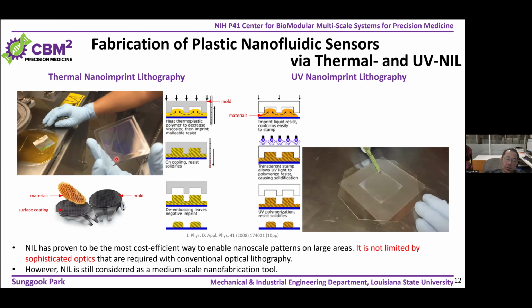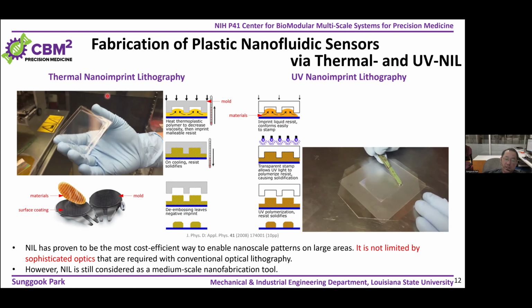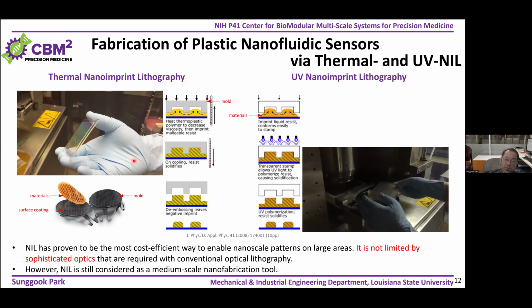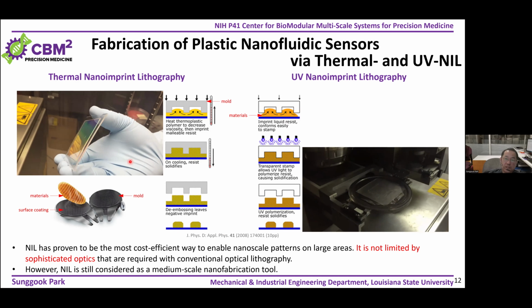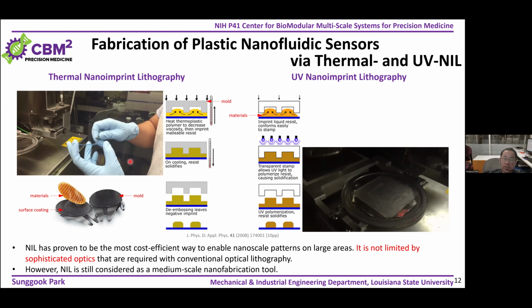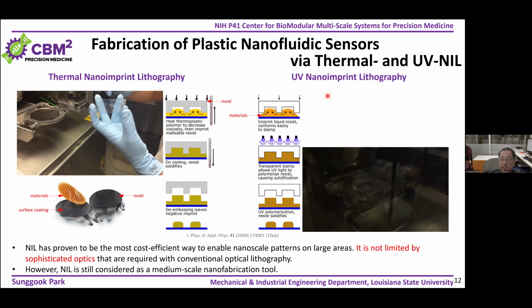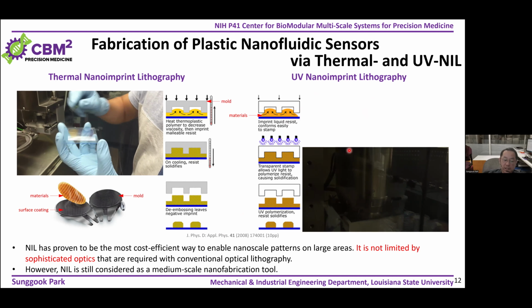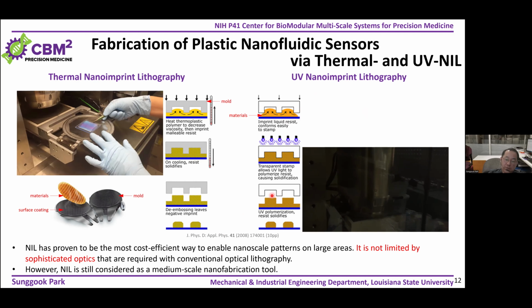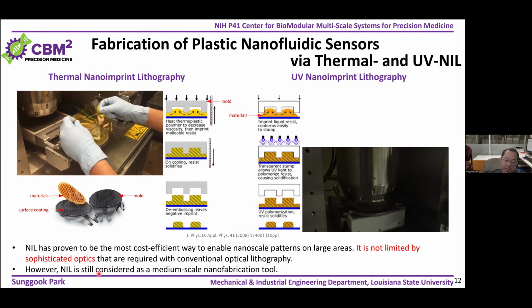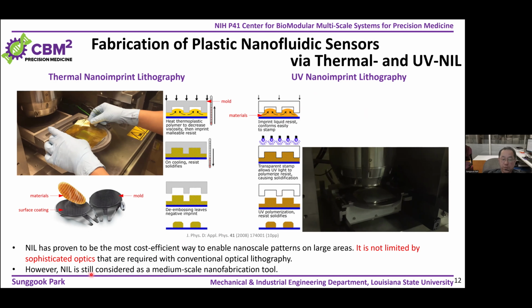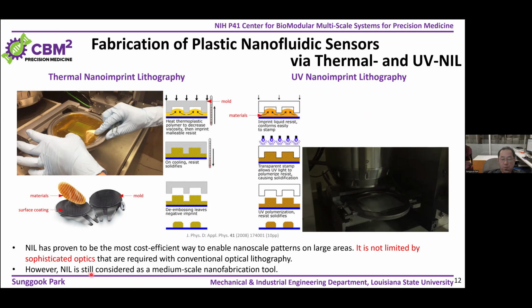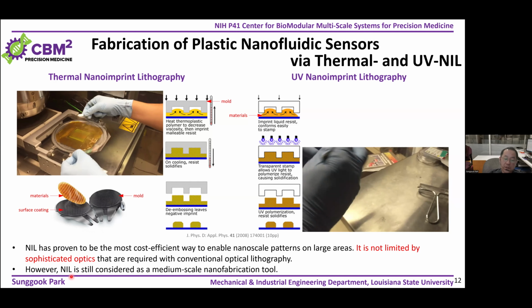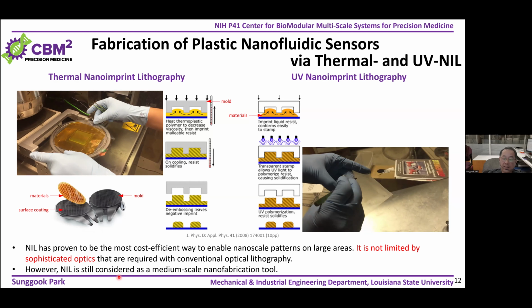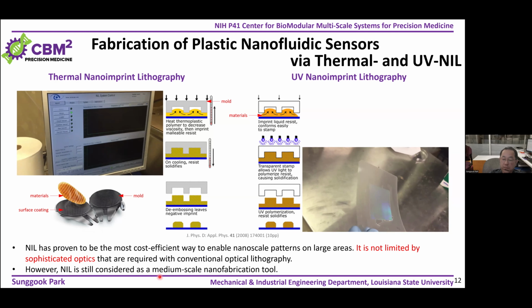But normally the process of producing one single sample with nano imprint lithography takes around 15 to 20 minutes. Sometimes if you have large structures, it goes up to 30 minutes. For UV nano imprint lithography, it's a little bit quicker. But still, around 10 to 20 minutes production time for a single sample cannot really be used for production of nanofluidic devices. So basically, nano imprint lithography can be considered a medium scale nano fabrication tool.